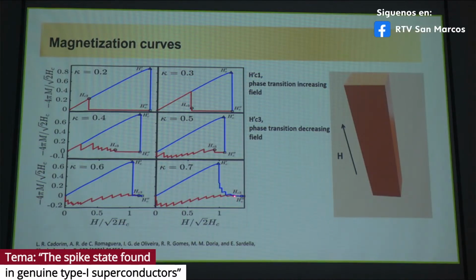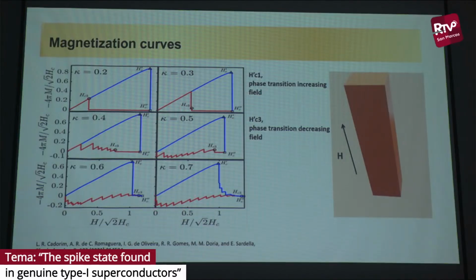When you reduce the applied magnetic field, there is penetration of vortices inside of this superconductor needle, and you have these jumps here. Each jump, like this one, is a fingerprint of the penetration of a vortex inside of this needle. Okay, and so in this case here, we have a, oh my God, what's happening?